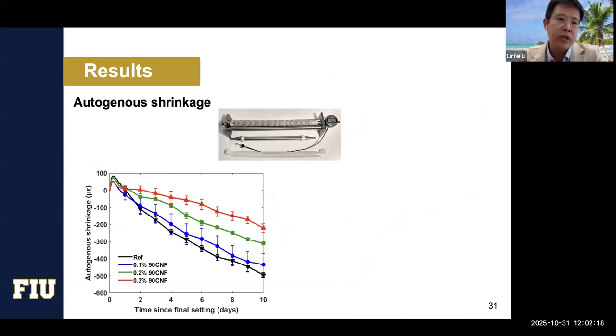And we also did the autogenous shrinkage test. This is the most important thing because it can quantify how our cellulose nanofibril surface agents can mitigate the shrinkage. So we got some pretty good results. As you can see, the reference sample had the largest shrinkage, up to 10 days, about 500 microstrain. And with continuously adding more and more CNF into the system, we're able to lower the autogenous shrinkage. From all the samples, we see there is an initial expansion.